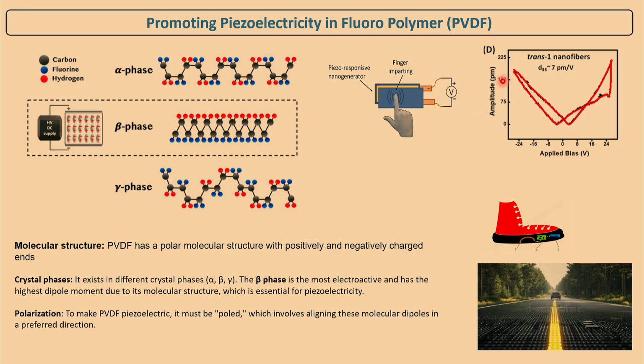And how do you follow that up? You can see something like this butterfly loop. If you look at the amplitude of the mechanical force and the applied bias over here, you can have a very nice butterfly loop like signature. It signifies that this material is piezo responsive, and you can quantify the D33 value, that is the coefficient of piezo response along this 33 plane. The higher the value you get, the more piezo responsive it is. It's very important. And you can think of piezo responsive as the sustainable future.